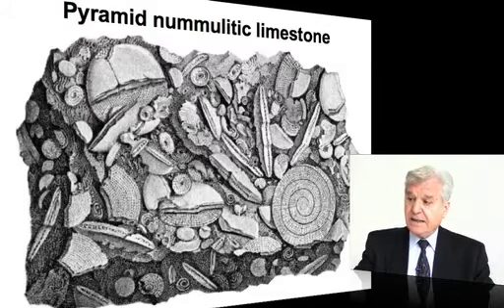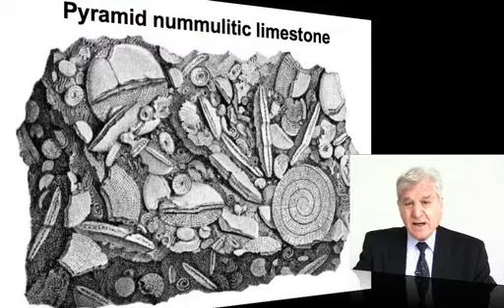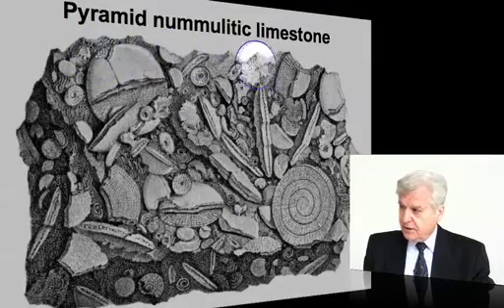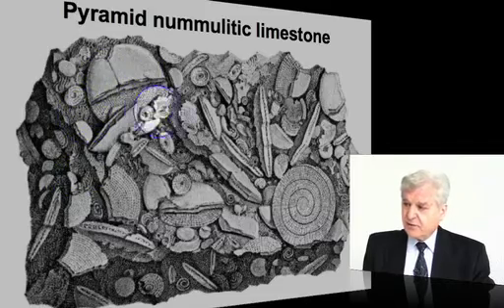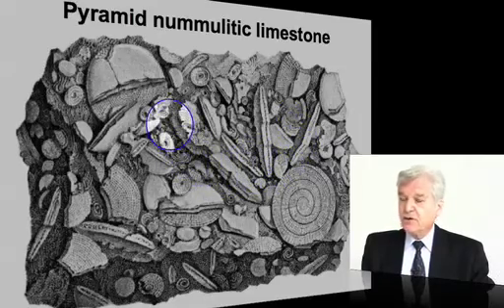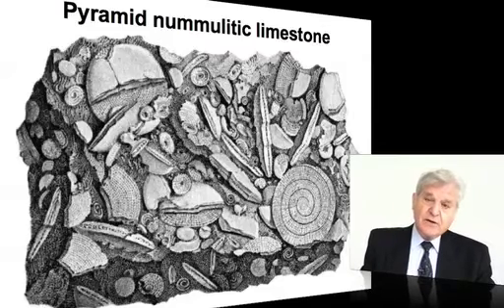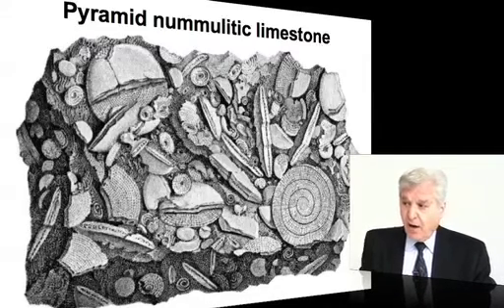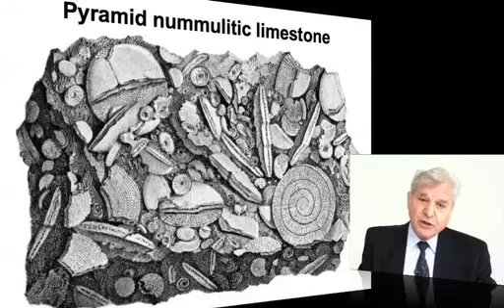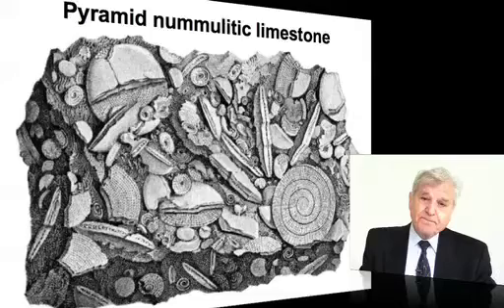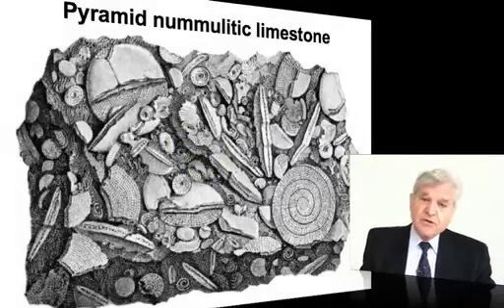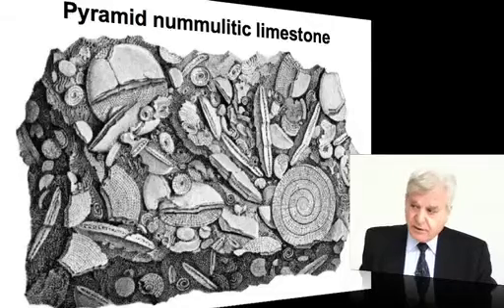The problem is that we are dealing with a material that is an aggregation of fossil shells. You see here the shells constituting the pyramid blocks. We have 95% shells and in between a very tiny amount of other binder called micritic binder. So when you make a thin section, it is obvious that what you see are the natural elements — the shells. 95% of what you have under your microscope is natural shells, and we are just discussing the 5% constituting the micritic binder, the geological glue.